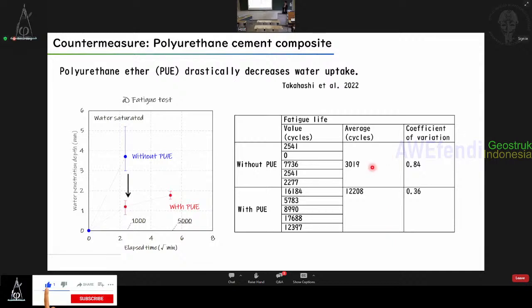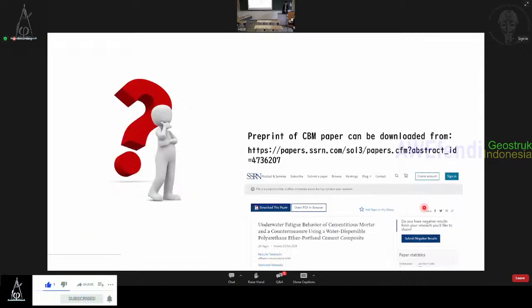If you do not get 3,000, but if you get 12,000, the coefficient of variation is also decreased due to the presence of polyurethane ether. Such a way can be a countermeasure for underwater fatigue.